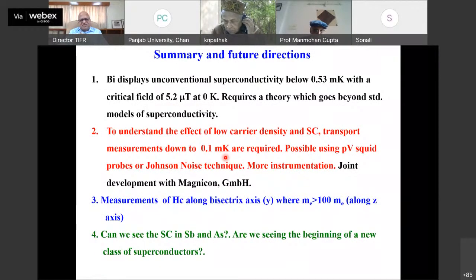Then the question is anisotropy. I showed you one anisotropic measurement. Since the bismuth is rhombohedral, we wanted to check along the axis how the effective masses change and so on and so forth, and what is the critical field which it gives. And can we see superconductivity in antimony and arsenic, which is also a semi-metal with a comparable concentration. So the question is, are we seeing the beginning of a new class of superconductors?